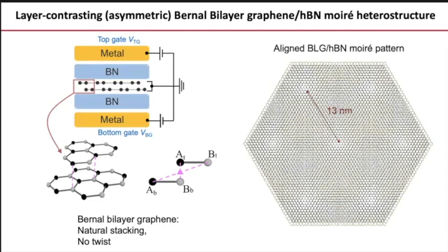So sort of by magic, it turns out that hexagonal boron nitride has a lattice which is very close to that of graphene, just a little bit different. And if you align the two lattices, graphene and hexagonal boron nitride, the Moiré pattern also happens to have a 13 nanometer wavelength, similar to magic angle graphene. But what I'm going to say is unrelated to that, okay? Just don't get confused by seeing the same 13. I'm talking now about the graphene to hBN Moiré lattice.